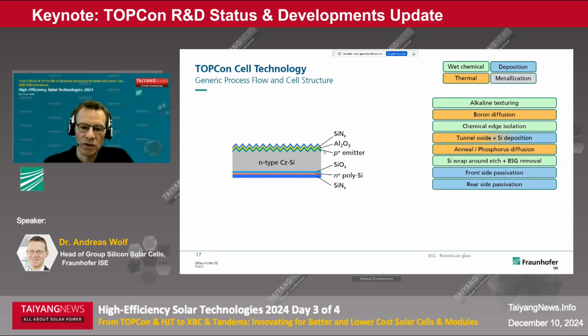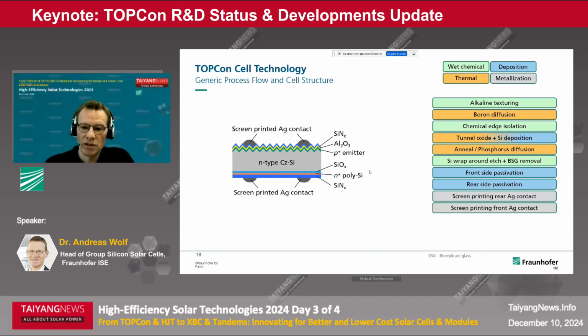Usually the front side is passivated by ALD aluminum oxide and silicon nitride or silicon oxynitride stack systems. On the rear side, silicon nitride based stack systems are also used. In some cases you also have aluminum oxide on the rear side, depending on the deposition technology that's implemented. And for the metallization, screen printing is state of the art. Meanwhile, you use silver paste without any aluminum content anymore due to the LECO technology.